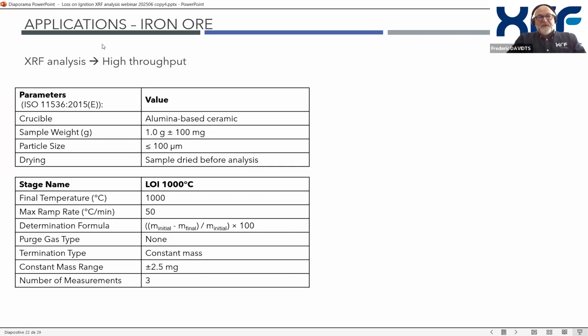Now, if we speak about XRF, what we require is a high throughput, so it must be fast. So the conditions are the same. We will work with 1 gram, but now we start with the sample dried. In a lot of sites, the sample is dried before crushing and grinding, etc. And if the product is packed quite quickly, we can proceed to the LOI analysis directly after, before drying it. So in this case, we will heat directly from room temperature up to 1000 with a ramp rate of 50 degrees per minute.